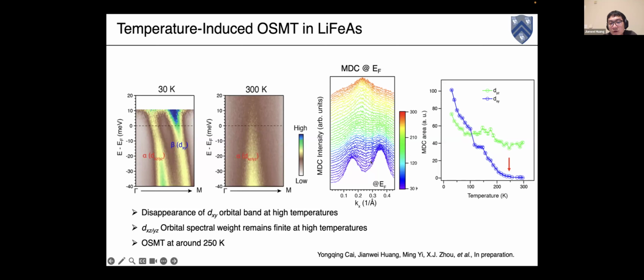And we can fit the spectra by two Lorentzian curves and extract the spectral weight. The dXY orbital spectral weight completely disappears at around 250 Kelvin. So this means that lithium iron arsenide goes into an orbital selective Mott transition at around 250 Kelvin.